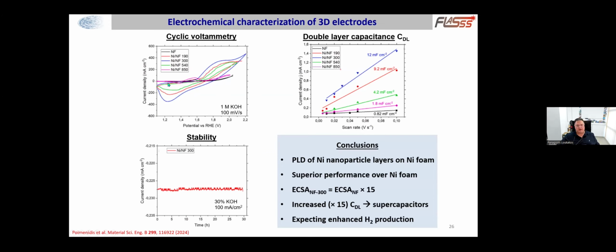And as you can see here, the films with a 300 nanometers thickness experience the best performance when looking at the cyclic voltammetry. Also, the double layer capacitance is increased for the 300 nanometers film, which makes it again useful for applications in supercapacitors. The stability is again very, very nice.